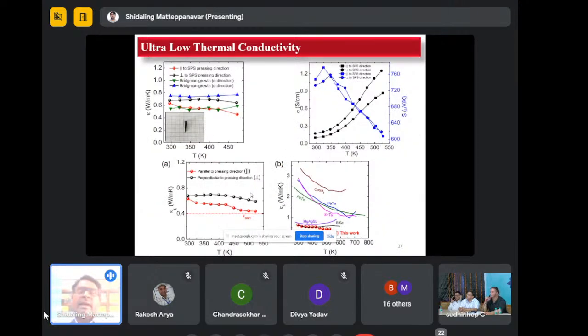with the I4/mcm space group, and we have obtained the lattice parameters and compared them with the reported values. Basically this material was prepared as a single crystal by the Bridgman technique, and we have also made the SPS